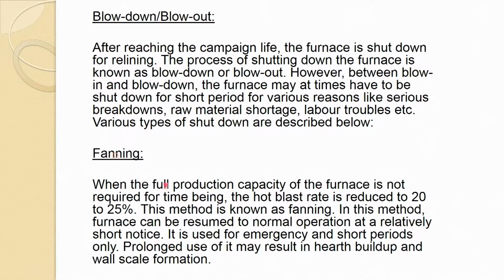One is fanning. When the full production capacity of the furnace is not required for the time being, the hot blast rate is reduced to 20 to 25%. Many times it happens that there is less demand and supply is more, so you have to reduce the production, and one of the reasons you can do that is by reducing the hot blast rate to this, or something at the downstream has broken down and then one has to take care of it.